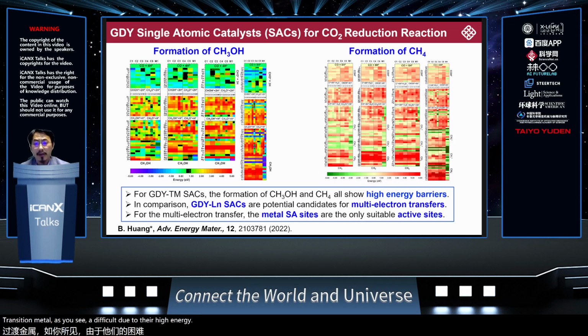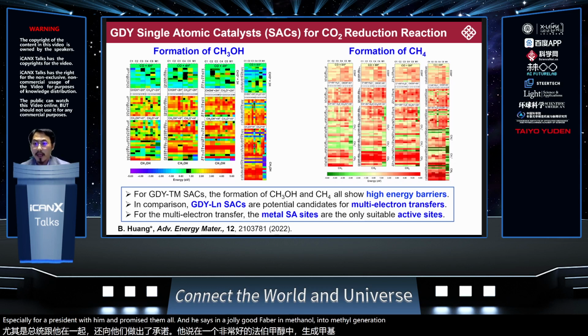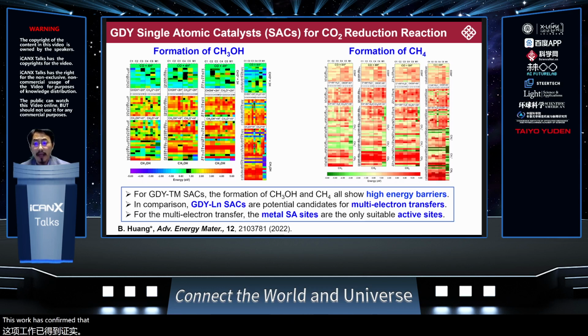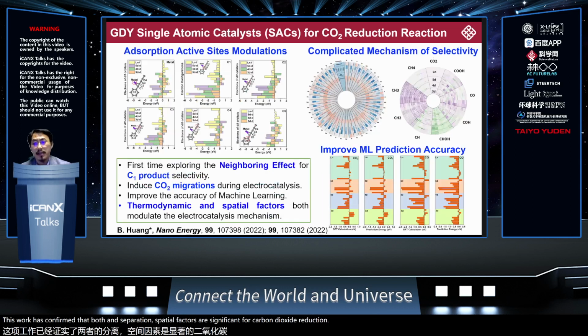high energy barriers of the hydrogenation process. However, these high energy barriers become much lower for lanthanide SAC, especially for praseodymium and promethium. All active sites are energetically favored in methanol and methane generations. This work has confirmed that both thermodynamic and separation spatial factors are significant for carbon dioxide reduction for SAC systems.